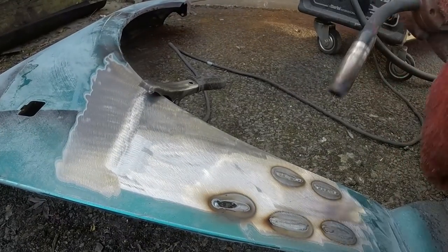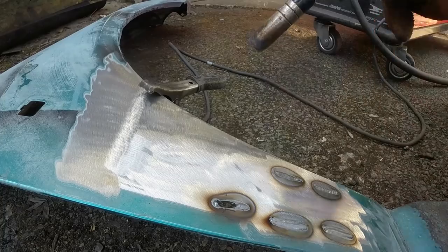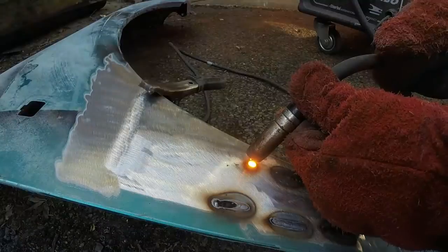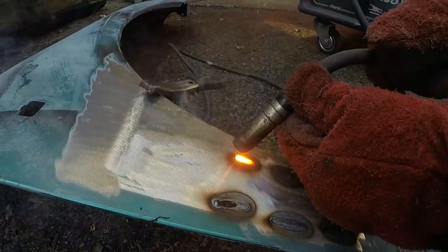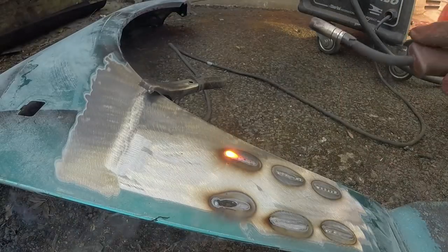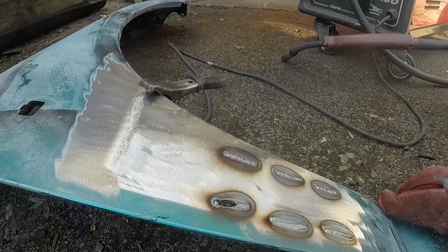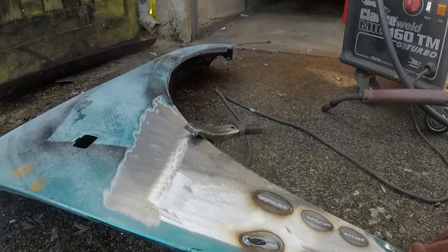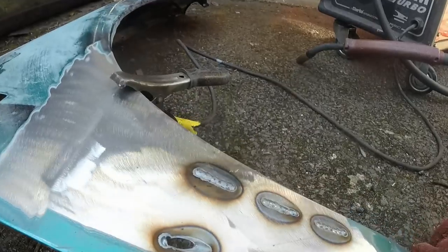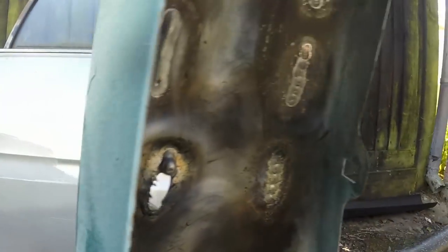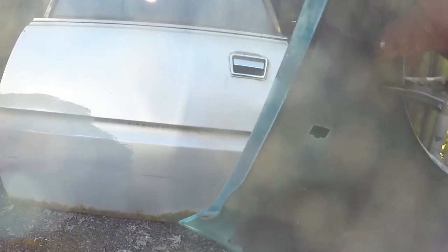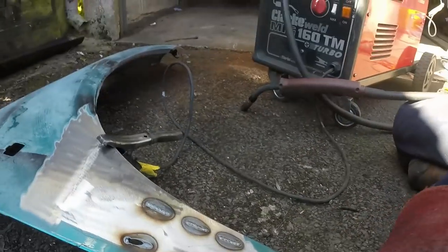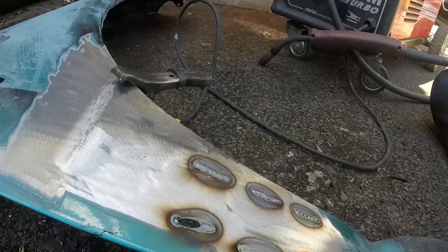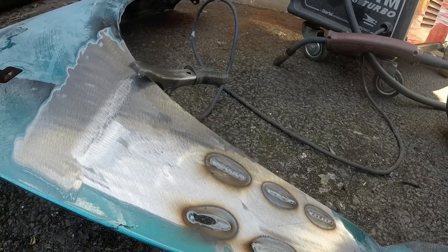Now I'm going to do this kind of stitched thing over about the same length. So massive heat distortion, but you haven't actually blown a hole, and yet you will have still ended up with a completely uniform bead of weld effectively. So that's why, reason number one, that when you see me doing my welding on Dotty, I'm doing that kind of a weld rather than stitch and seam welds. It reduces distortion, prevents blowing holes, and yet still leaves a decent penetrated weld.